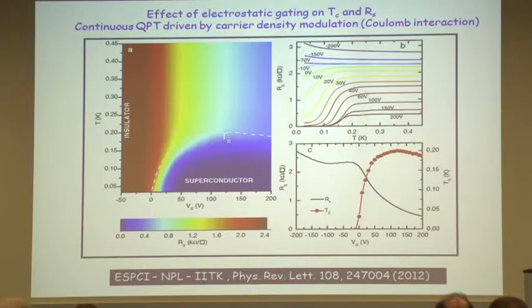Now, we can tune this superconducting state by applying the gate field. It becomes a very important tuning parameter. And as you can see over here, this is a slightly different sample. At zero gate voltage, you barely see the onset here. Apply a positive gate, the TC goes up. Apply a negative gate, the sample becomes non-superconducting.